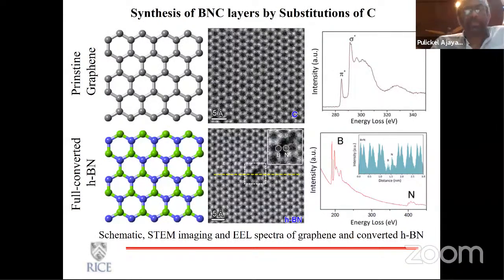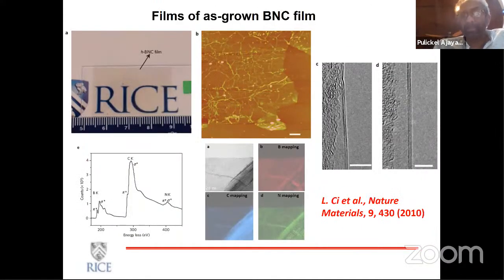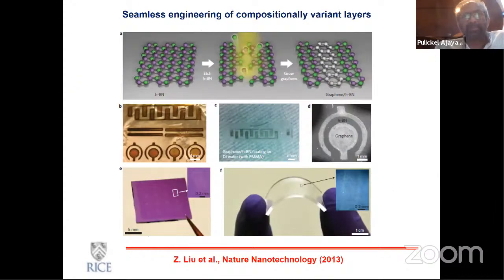Either you can grow directly these layers with the precursors that I mentioned to you, or you could start with carbon and actually convert that carbon into boron nitride using high temperature reactions. And we can follow these pretty nicely, how some of these systems are formed. But I just wanted to mention that because there are various different ways of growing these structures. Again, just like graphene or graphitic structures, these kind of films can be grown highly crystallized with all these three components. But if you look more carefully, you will see this domain structure that I mentioned.